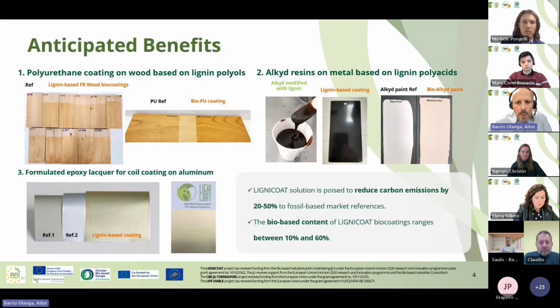Here you have some examples. The project is close to finish in November, so we have quite a new development. The first one is the polyurethane-based coating based on the developed lignin polyols. You have here some pictures. Other development is the alkyd resin that is based on lignin polyacids, modified lignin polyacids for protection of metal. And also we have formulated epoxy lacquer for coil coating on aluminum.